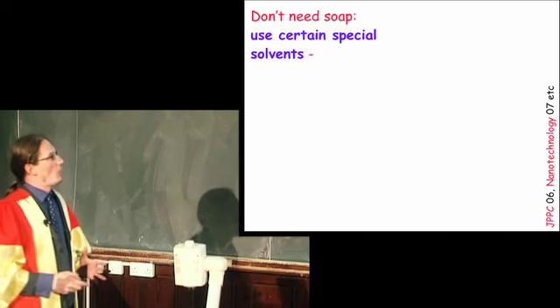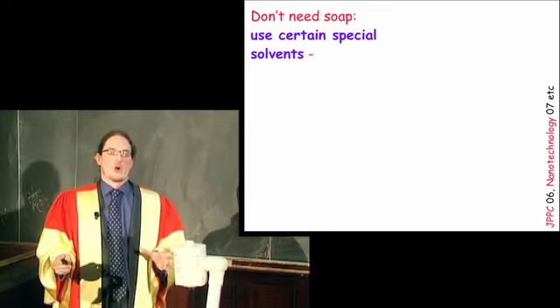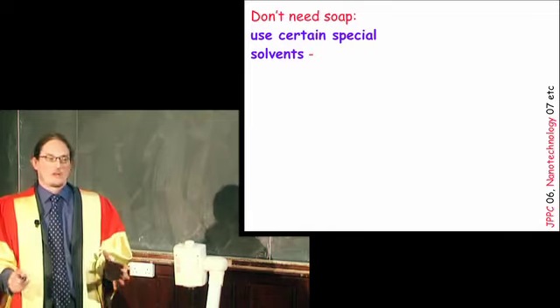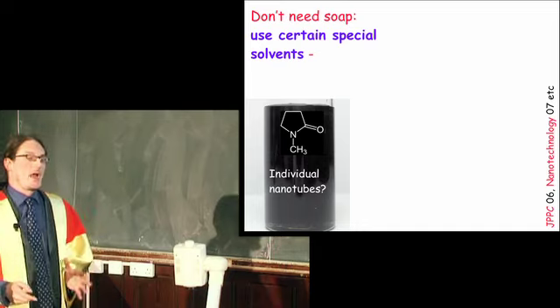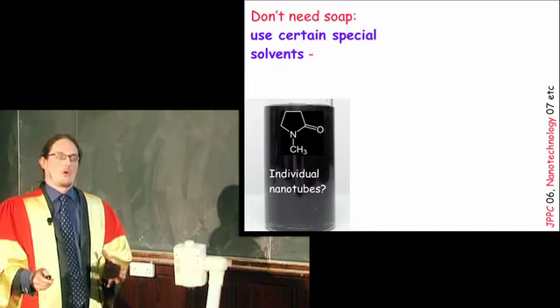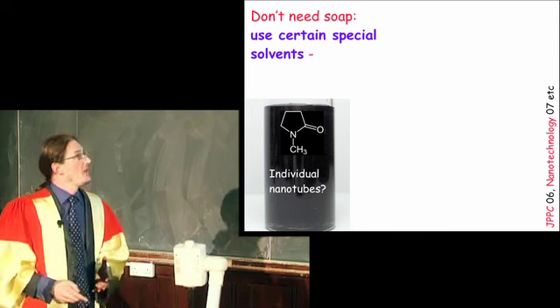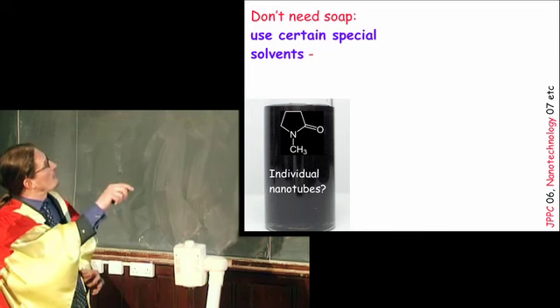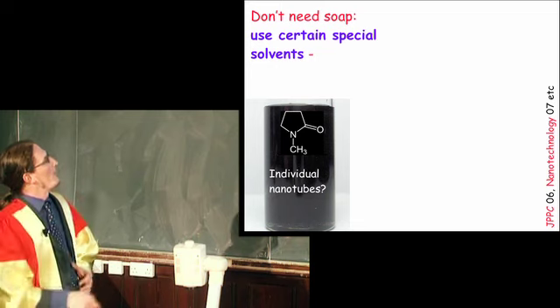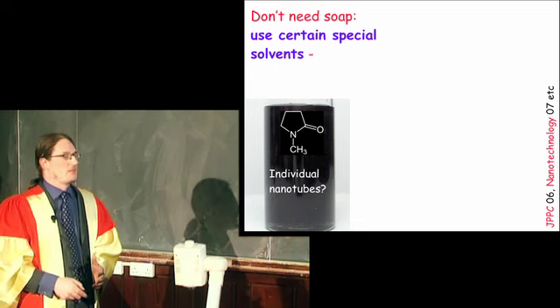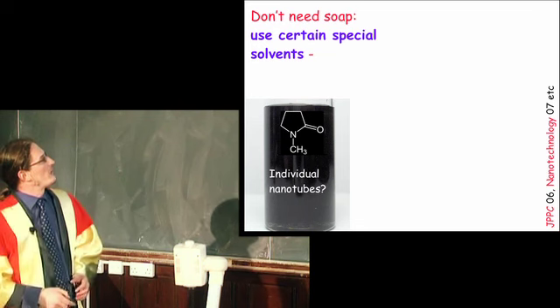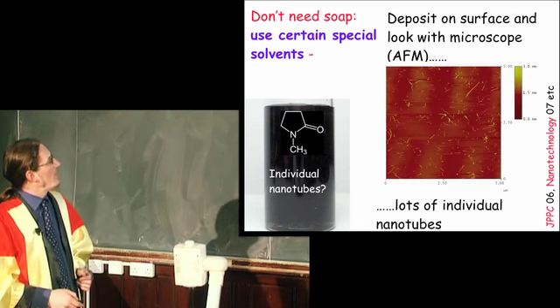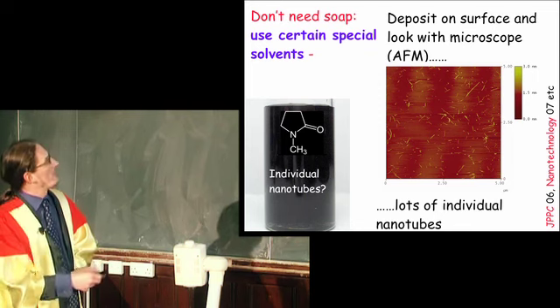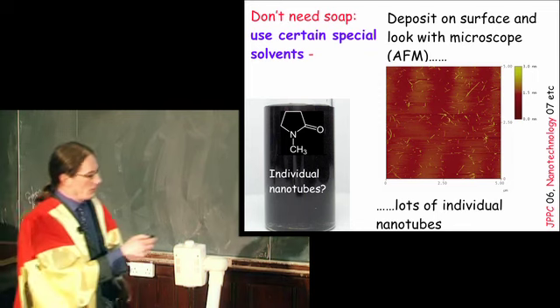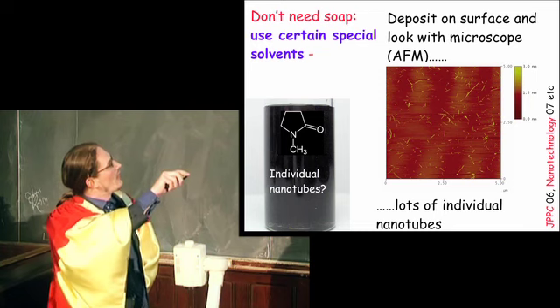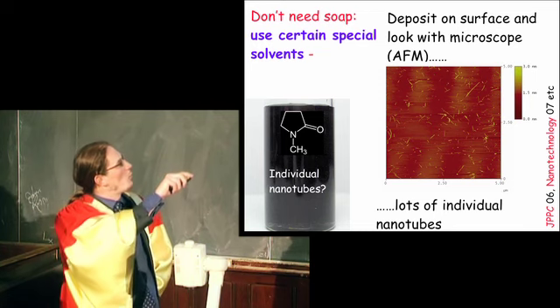Now, I talked about using soap, and for some applications you don't want to use soap because the soap gets stuck in there and it's hard to get it out afterwards. A simpler way would be to use just a liquid, or in chemical terms, a solvent. It had been shown that nanotubes could be dispersed in this solvent, but it wasn't known if the nanotubes could be individualized. So we repeated the work that had been done in a university in the States, and then we deposited some of this stuff on a surface, and you look at it with a microscope and you see you've got a large quantity of individual one-dimensional objects.